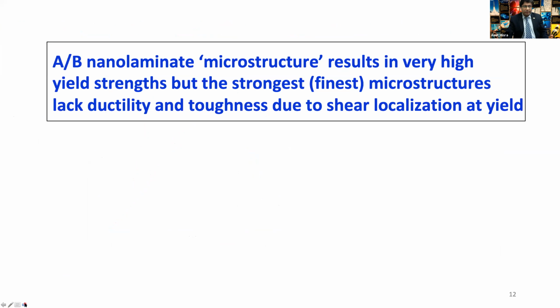So to summarize this part, what we've known from the literature, from the work that's been done, is that you can create an AB, where A and B can be 2 different metals or alloys, nanolaminate microstructure, get very high yield strength, but the strongest, which is the finest microstructures, lack a uniform deformation. They lack ductility and toughness because the mode of deformation becomes shear localization at yield.